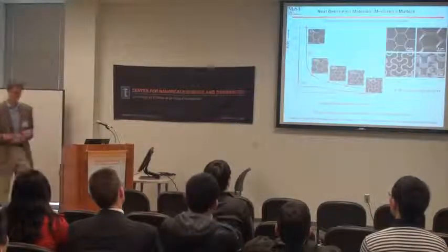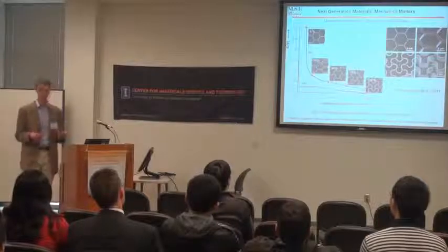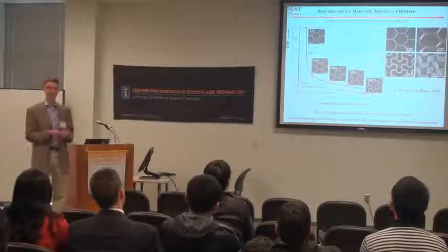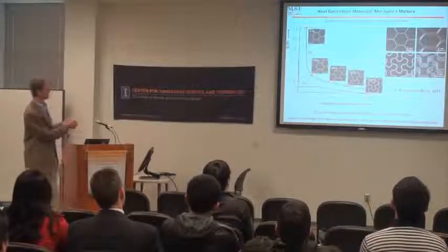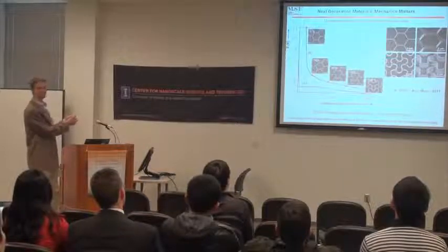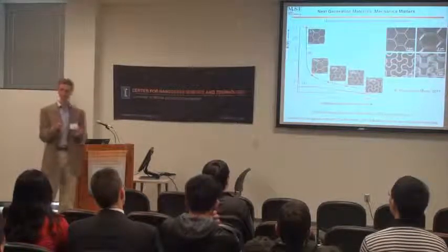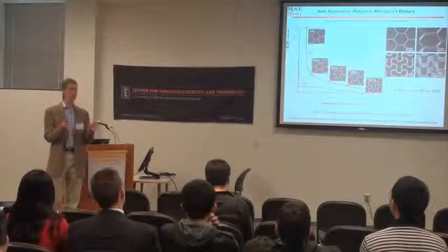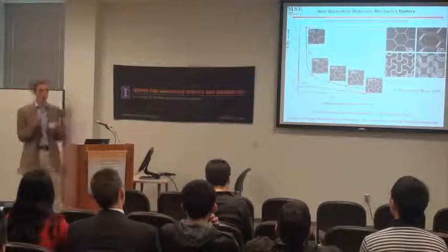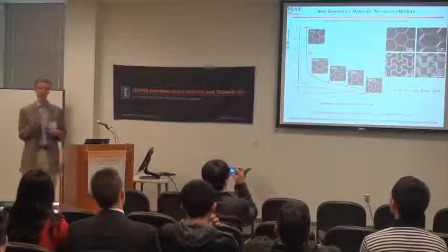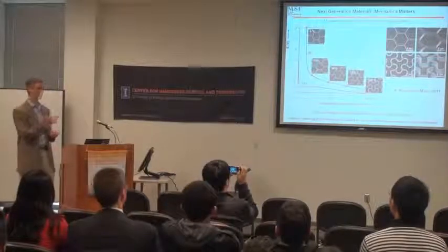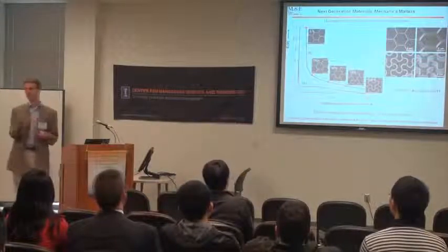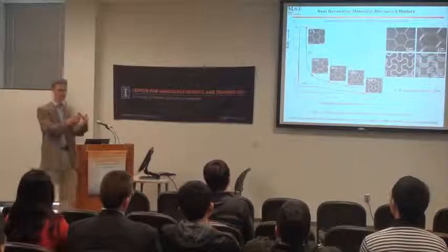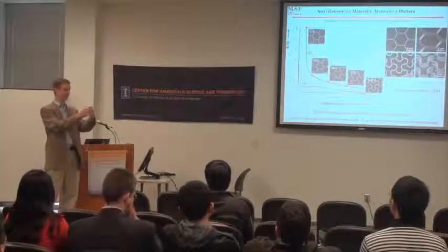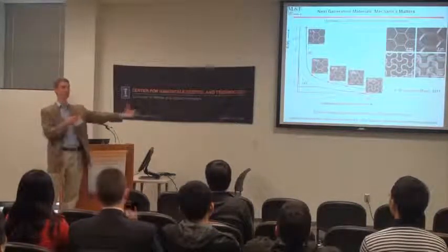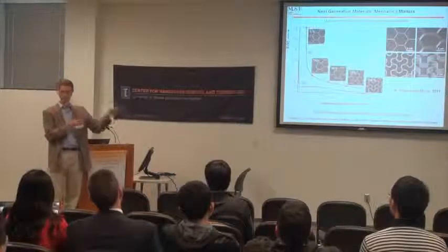So something fun. So far we've talked about conventional materials, and we'd really like to go to some materials that have much higher energy density. You may have heard of silicon. Silicon's an outstanding material for storing lithium with 1 or 2 minor problems. The first minor problem is that when you insert lithium into silicon, its volume changes by up to 300%. So how do I design a battery inside a steel can where one of the electrodes is changing in volume by nearly a factor of 4?